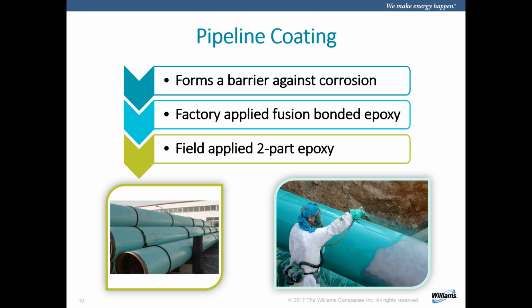Okay, I believe I'm on the pipeline coating slide. So after the pipeline has been tested, let me just back up. Previously, years ago, when pipeline came out of the factory, it just came as pipe without coating on it. The coating is now placed. Most cases, pipe out of the mill comes with the coating on it, and the whole point of pipeline coating is to form a barrier against corrosion that will prevent or mitigate the metal loss of leaving the pipe and going to the natural earth.